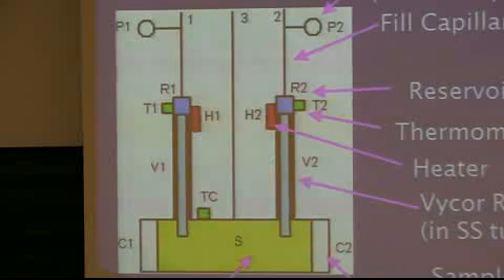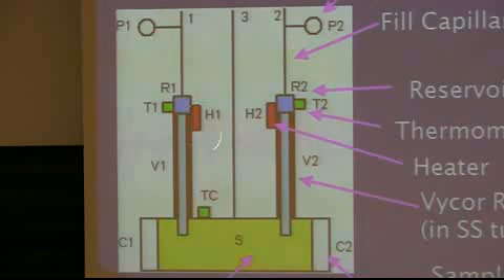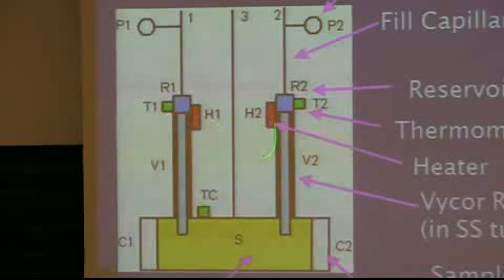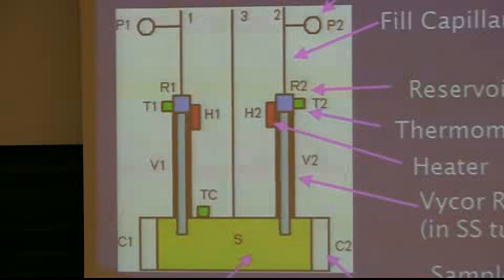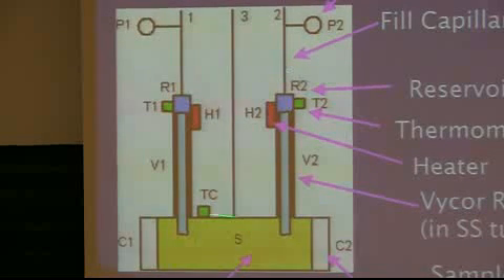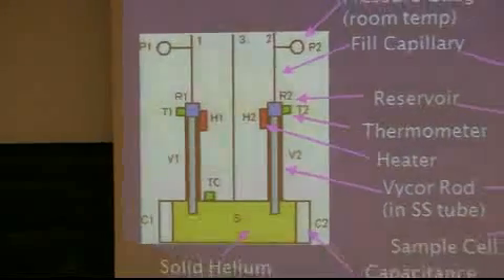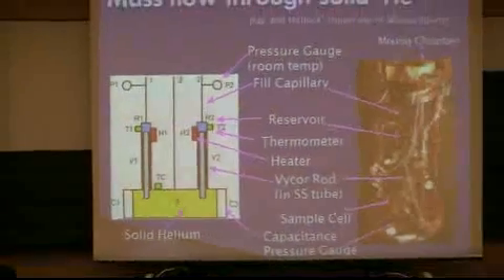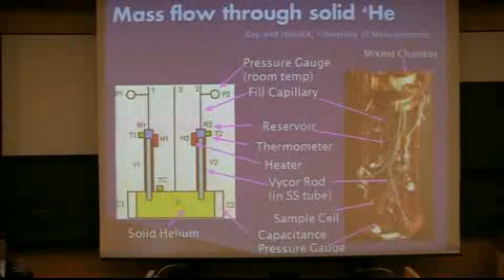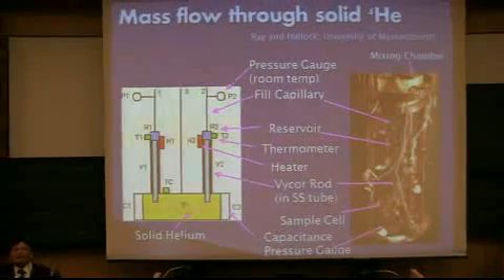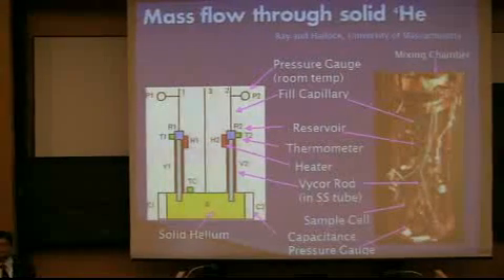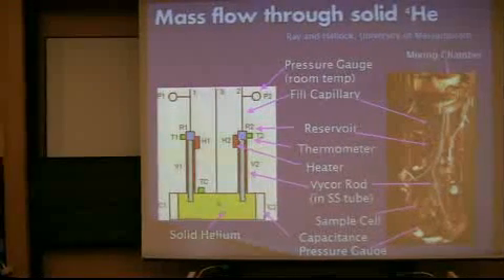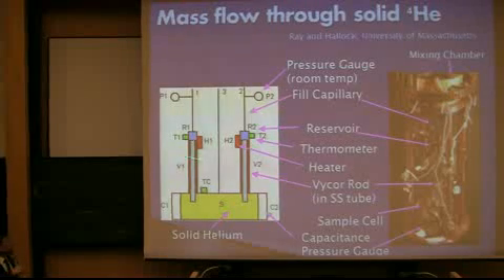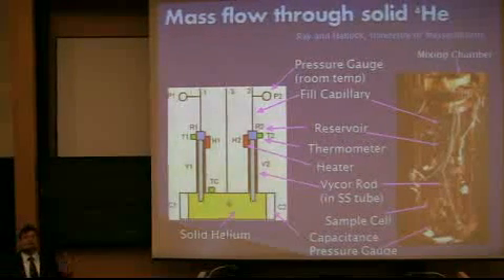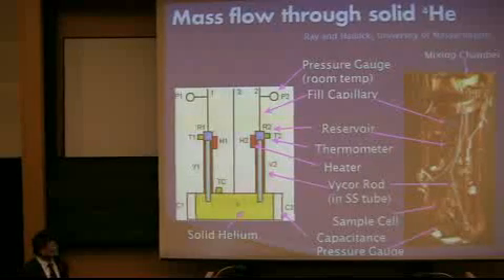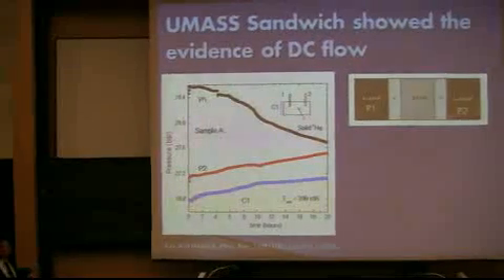Also, in the second part of the experiment, they change the temperature by heating one side of this chamber and see if there is any flow through it from the other chamber. This is the so-called thermomechanical effect that was first seen in superfluid helium. Usually you expect that because of the entropy, the flow of liquid is generated from hot to cold, right? However, if you have a superfluid, then you have flow from cold to hot. So when you heat one side of the chamber, there will be a drag flow through the solid helium from the other side. So these are the two experimental results that I'm going to show you here.